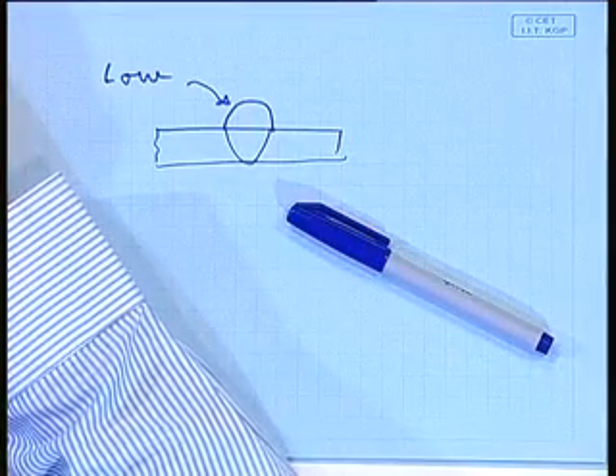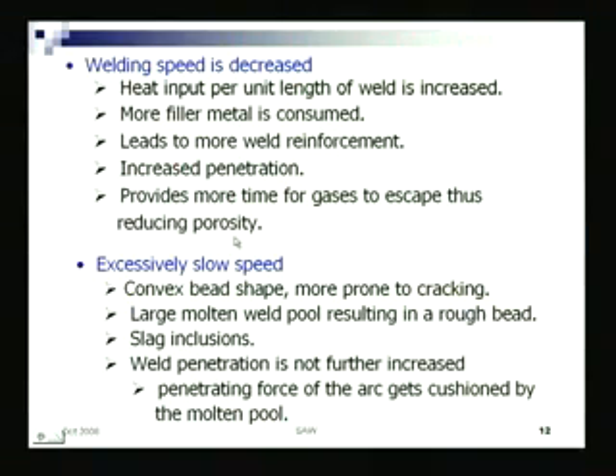But it provides more time for gases to escape, thus reducing porosity. Chances of porosity will be much less. Further, if we reduce speed further, we get a very convex bead shape, more prone to cracking, a large molten weld pool resulting in a rough bead, slag inclusion might take place. Weld penetration is not further increased, as we have talked about, because the penetrating force of the arc gets cushioned by the molten pool.